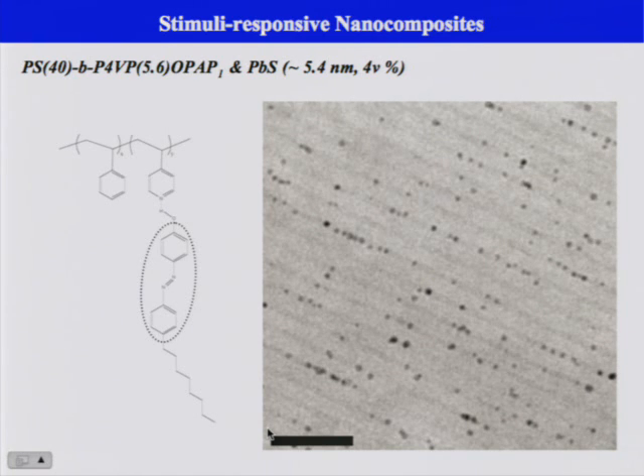This is an azobenzene-containing small molecule, and by shining UV light on it, we go from the trans state to a cis state. The ring flips up, forming this cis conformation transformation. As the small molecule changes its conformation, the particle is driven around.